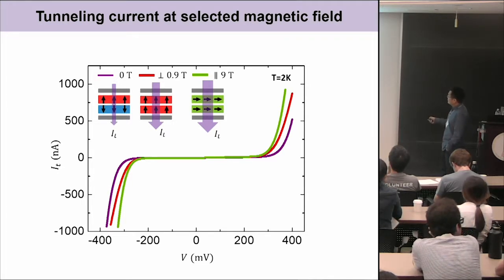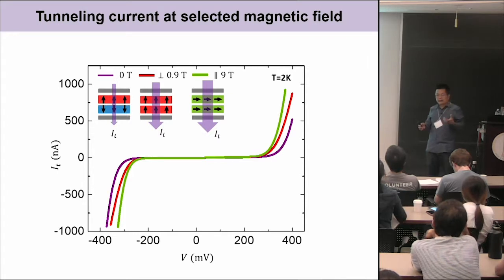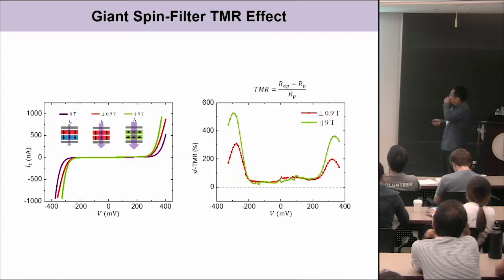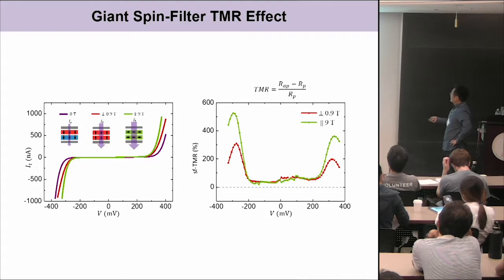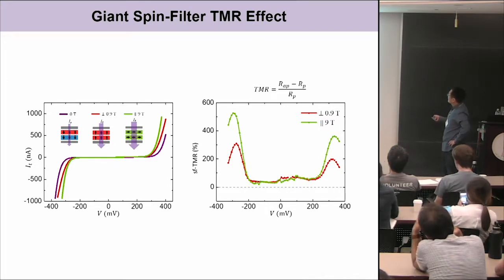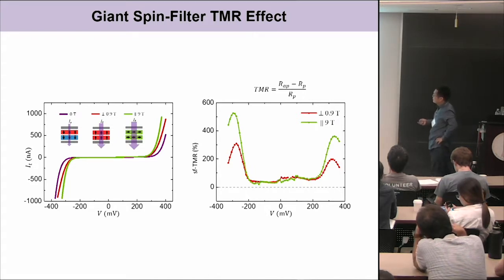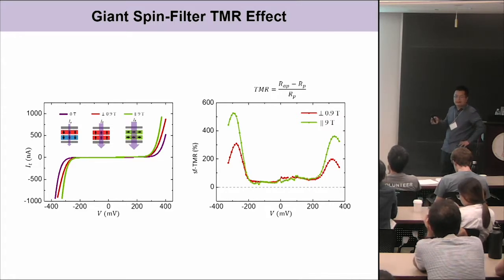The difference between the spins aligned out of plane and in plane comes from what shows up as an anisotropic magnetoresistance in the system. So we can define the tunneling magnetoresistance following these definitions. And we found that for bilayer, we can already get a TMR on the order of several hundred percent, right? From 400 to 500%. So this is already much larger than the europium sulfide system you can get and close to the state of the art of MgO systems.